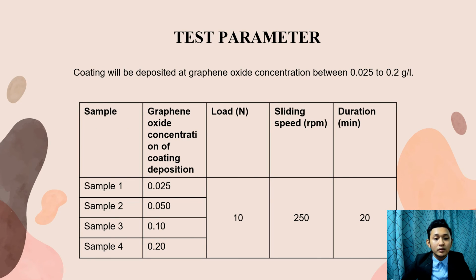Test parameters. Coating will be deposited at graphene oxide concentration between 0.025 gram per liter to 0.2 gram per liter. We have 4 samples. Sample 1 we will use 0.025 gram per liter. Sample 2 we will use 0.05 gram per liter. Sample 3 we will use 0.1 gram per liter. Sample 4 we will use 0.2 gram per liter. Load we will fix at 10 Newton. Sliding speed we will fix at 250 RPM. Duration we will fix at 20 minutes.